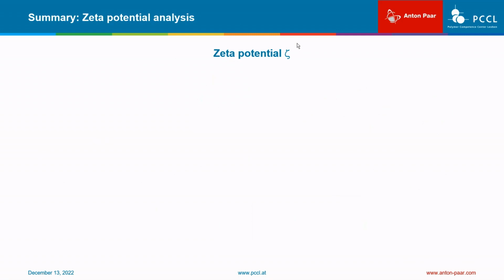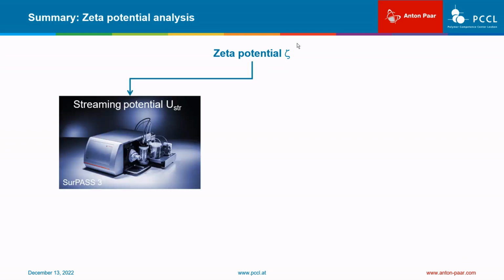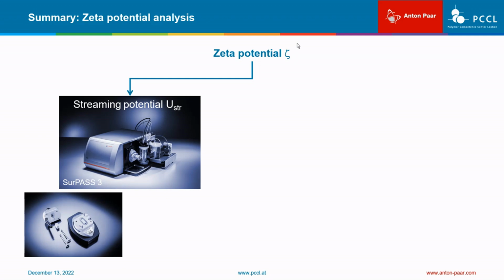Thank you, Inge. Now that you have seen a series of Zeta potential results for various applications involving polymers, it is time to give a short summary on the two methods for the Zeta potential analysis. The majority of data that we have shown was recorded by the measurement of the streaming potential, and the instrument Surpass 3 is the latest instrument for the surface Zeta potential analysis at Anton Paar. A typical sample holder, for instance, for polymer films is the adjustable gap cell for creating a rectangular flow channel between a pair of samples with a flat surface.